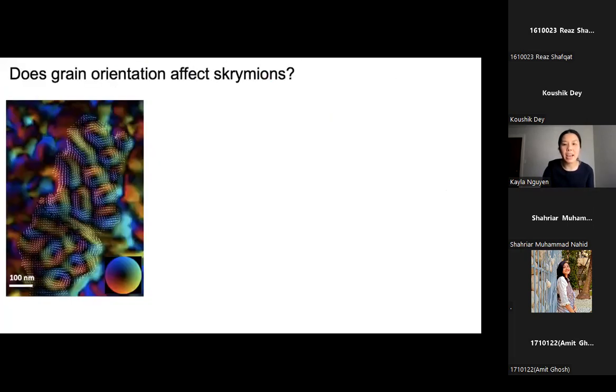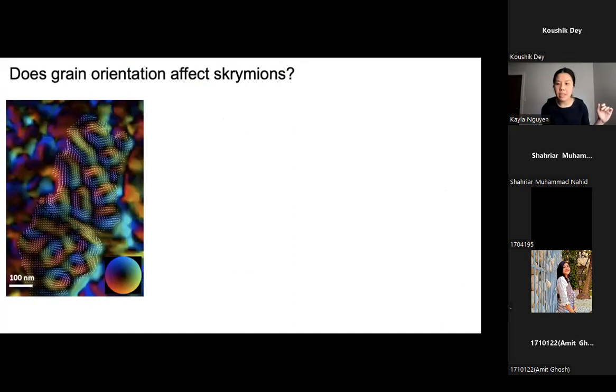Yes, so I do have the temperature for this one. This is at 100 Kelvin, so nitrogen temperature, and we're applying a field of 100 millitesla using our objective lens. So we're turning on the field a little bit to get them. I would say they're pretty stable at liquid nitrogen temperature and with applied field, they don't change. But you can also do, for example, in situ Lorentz microscopy, where you can change the magnetic field or the temperature, and these magnetic vortices would go away. But in our experiment, we find that they're pretty stable at liquid nitrogen and at a field of 100 millitesla.